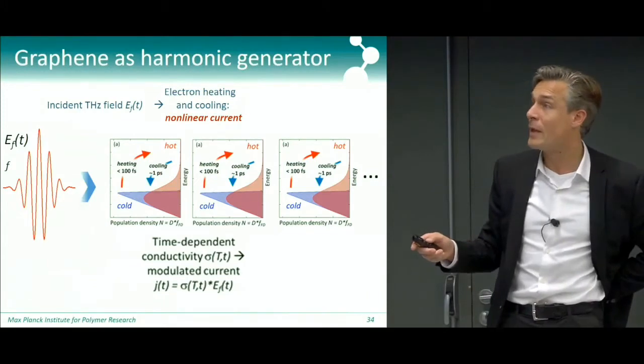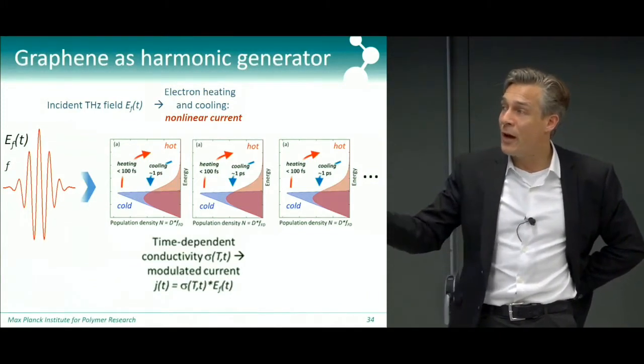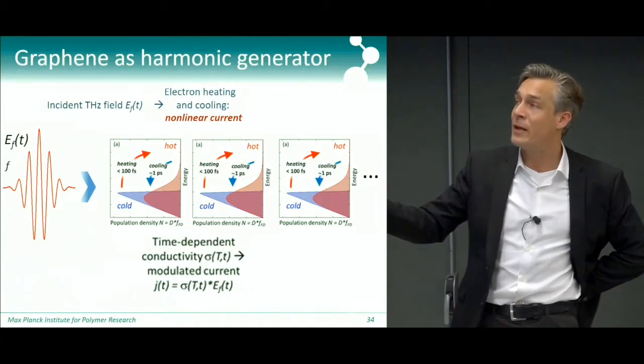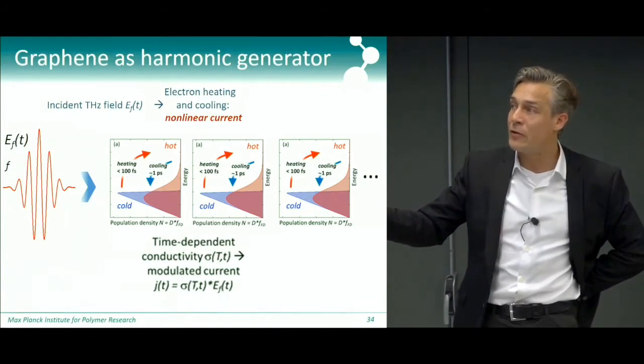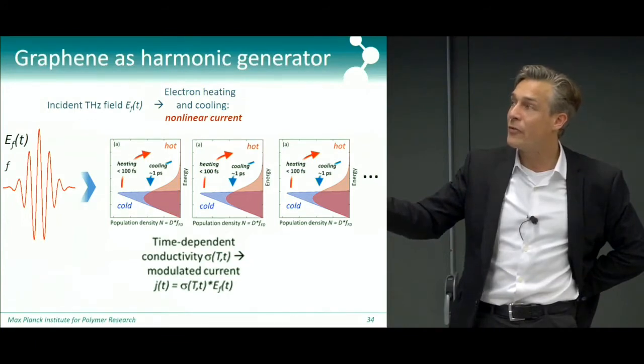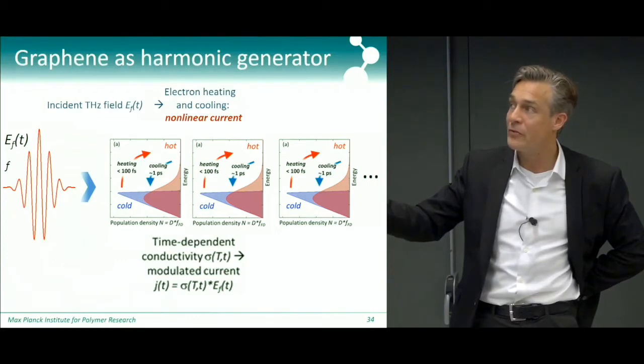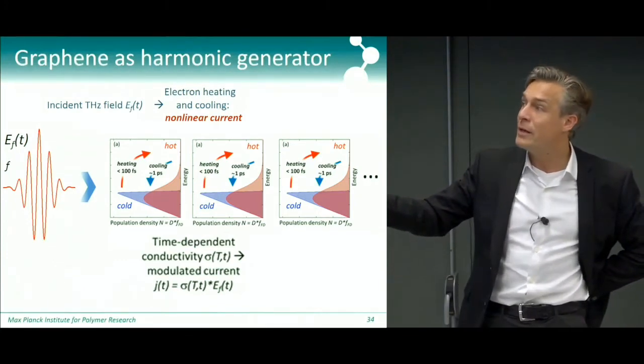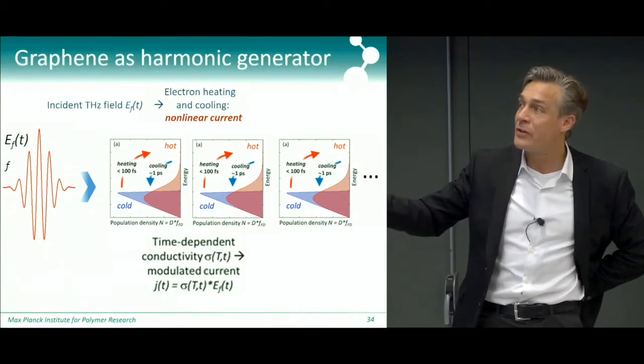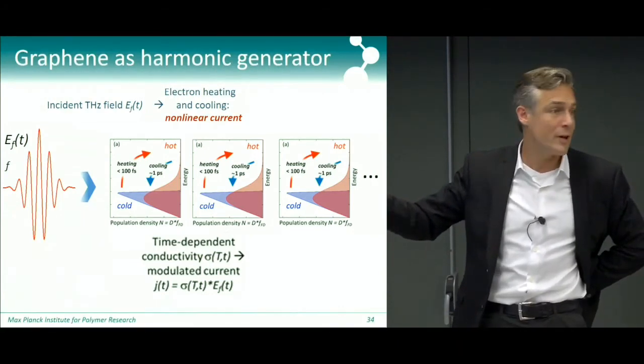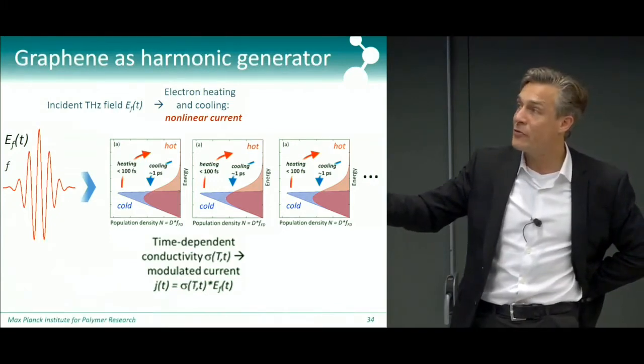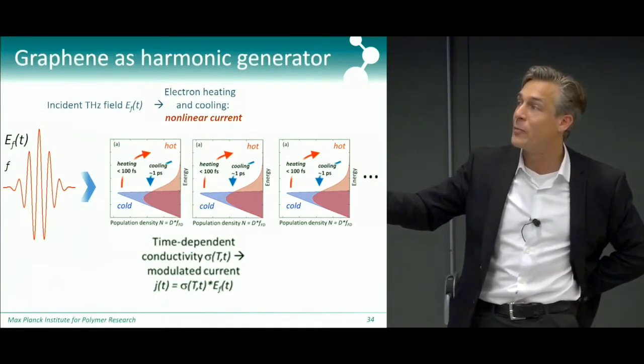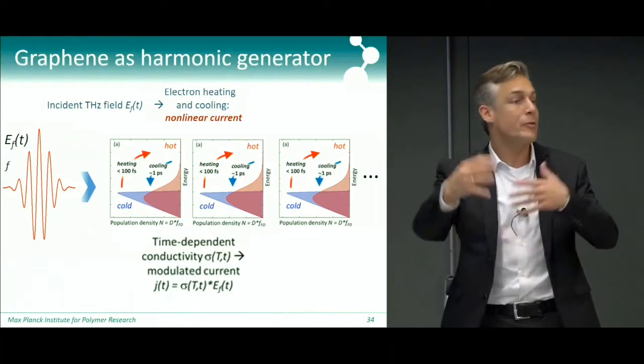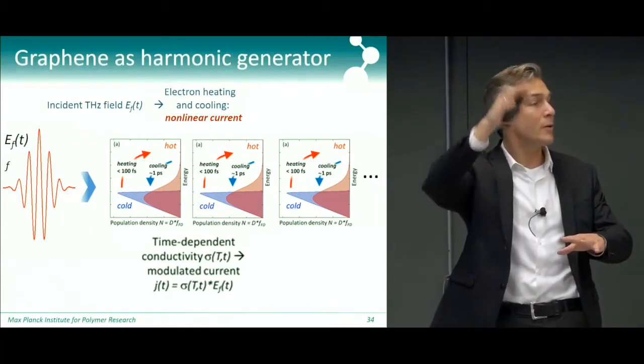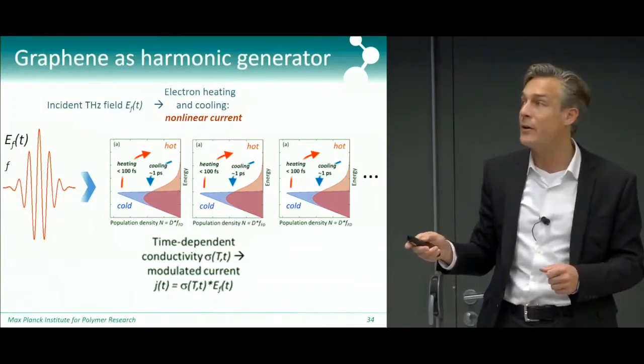That was the idea. And so this relies on a very strange effect, namely that during the cycling of the terahertz pulse, you get cycles of heating the electronic distribution. So it looks like this, and we have this greatly reduced conductivity. Then between cycles, essentially, cooling takes place, because the oscillation time here is about a picosecond. So there's substantial cooling occurring before the next cycle of the pulse comes, which heats it again. So you keep going through these cycles of heating and cooling and heating and cooling. And this is what gives rise to the nonlinearity.